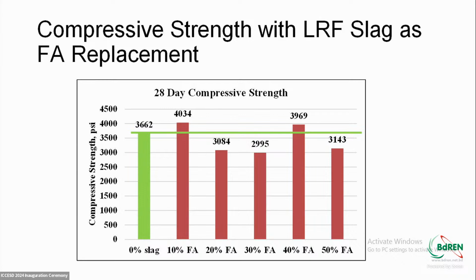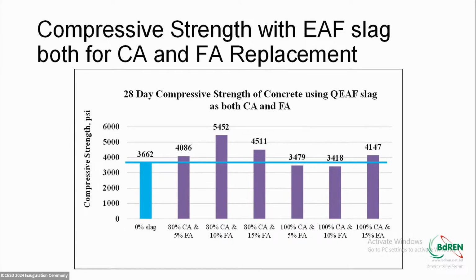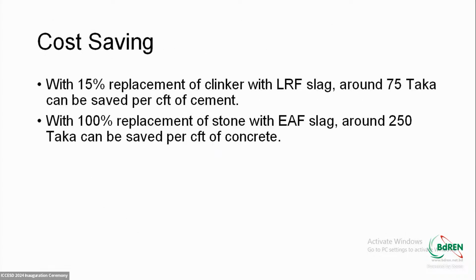So finally, what we can say is that even when we use EAF slag as replacement of both coarse aggregate and fine aggregate together, the result varied. So finally, what we can suggest is that for coarse aggregate replacement, EAF is a very good choice, but fine aggregate replacement is not desirable—that's number one.